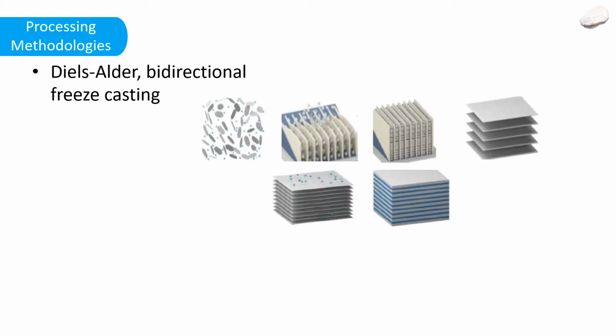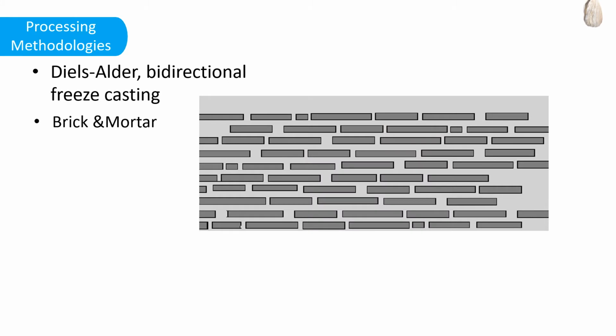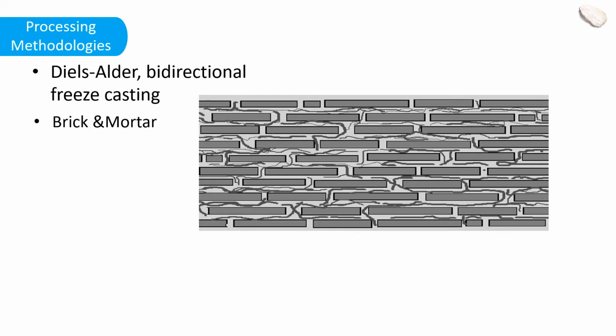Scientists have come up with several processing methodologies to mimic nacre-like composites. Diels-Alder polymerization with bidirectional freeze casting is one such method, where alumina slurry is introduced into a mold and bidirectionally freeze casted to obtain a mechanical scaffold. The scaffold is then pressed and calcinated to densify it to obtain a smart nacre. Brick and mortar arrangement is another method, where the brick forms the rigid part and the mortar forms the polymer soft part.